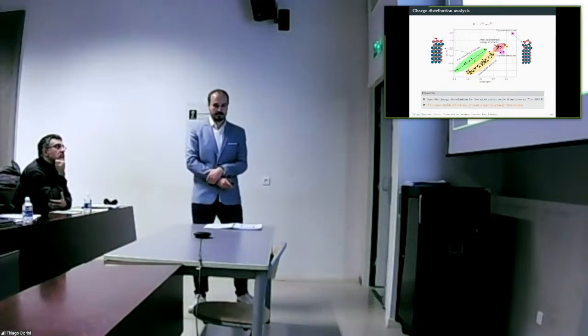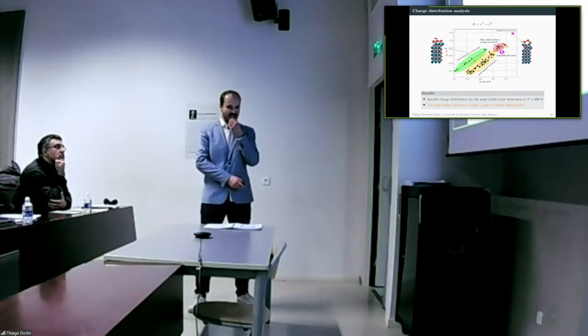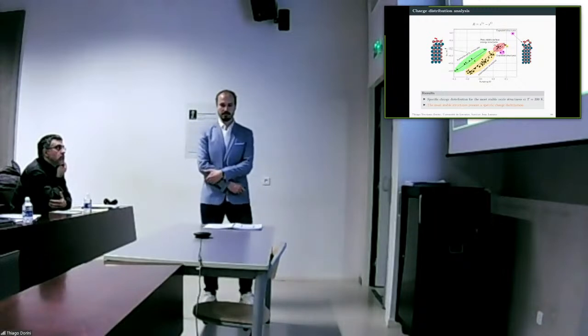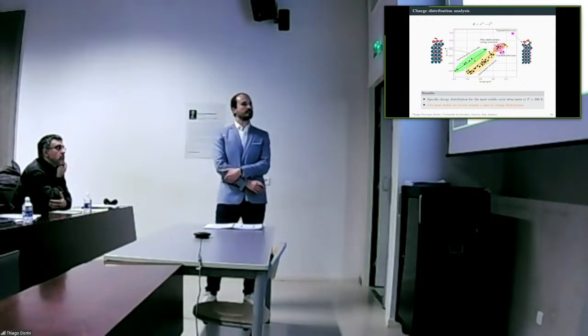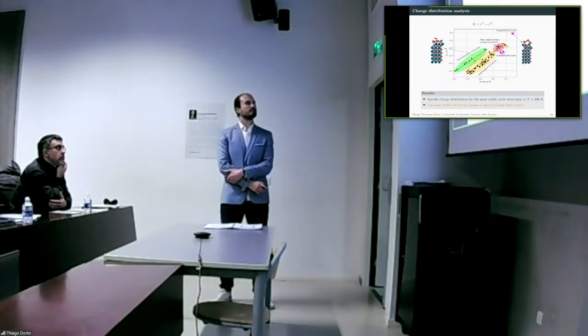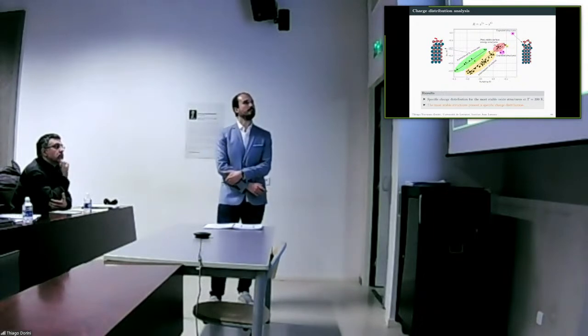The oxygen atoms from this oxide layer are really reactive, notably with some gases to react and dissolve. They can be added on the surface and removed from the surface, and this is some kind of catalytic cycle through the reduction or oxidation of the surface. If you do not have any vacancy below, the O2 is not stable at all above this surface. But once you have a vacancy, you will favor the interaction of the O2 on the vacancy.